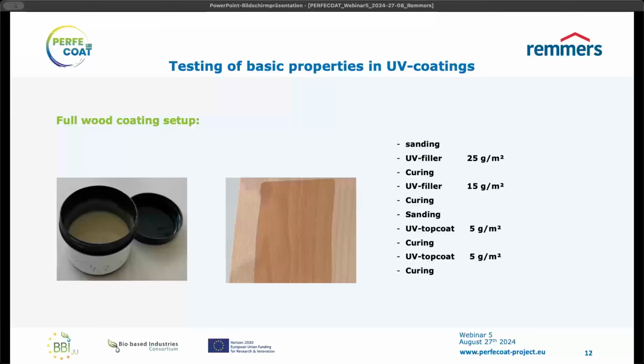Then we do the curing of the filler, an intermediate sanding to get a nice and smooth surface, and afterwards the UV top coat is also applied in 2 layers, 5 gram each, with intermediate curing, and then of course the final curing. And these surfaces will be tested and compared to fossil-based benchmark, and hopefully soon we will have some more promising results.